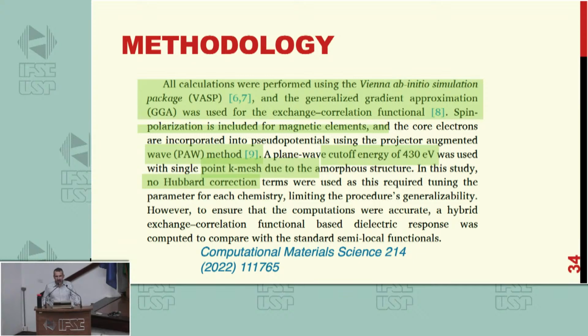Hubbard correction, this is getting very complicated. So when you treat transition metals, you have d electrons, and DFT, GGA, in these methodologies, they are not very good dealing with transition metals, okay? If you take rare earths, f electrons, it's even worse, okay? So we struggle, we can do that, but you cannot use just the standard recipe that comes with the code and run it. You have to put some extra spice in the code, extra ingredients in order to get your result, and that's the Hubbard correction, okay?